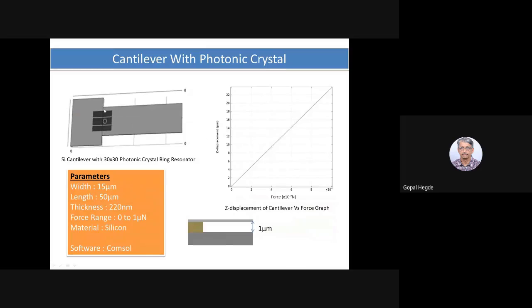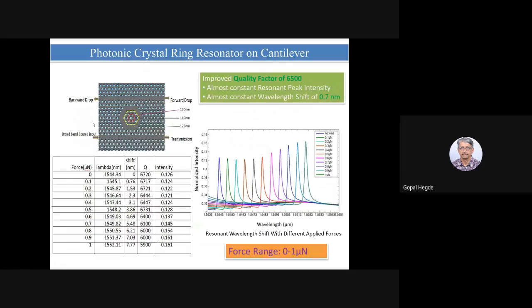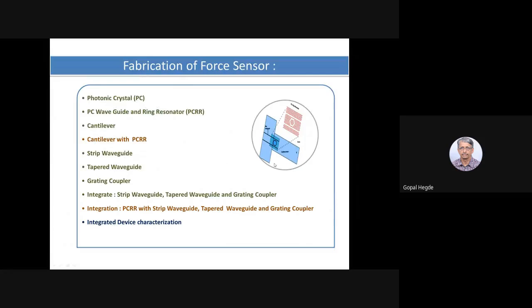Here you see, whatever force is falling on this one, there is a shift in the resonant wavelength. When you launch the light from this end, because of the force, you can measure the light output from this waveguide here. When we modeled, we saw that it's possible to measure the force. This is the wavelength shift, and we modeled this with 0.1 micronewton to 1 micronewton force applied. We saw this much shift here. So this is a model. Whether it is really possible to fabricate it was the challenge for us, and we started this project and we did it.